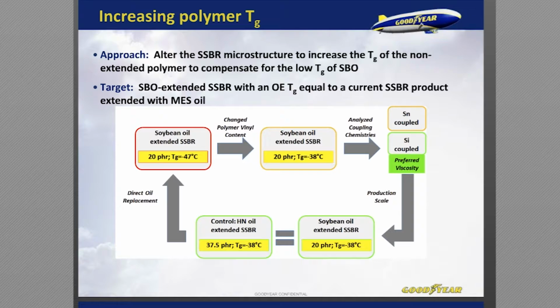Well, what we could do is alter the polymer microstructure to accommodate soybean oil. So what does that mean? We have a current inline commercialized styrene butadiene rubber that is extended with petroleum-based oil. It has a glass transition temperature of -38, and that's all important in our compound formulations, and how we put everything together. But glass transition temperature is very important because that really gives us our wet rolling resistance and our wet winter balances in our tread compounds.